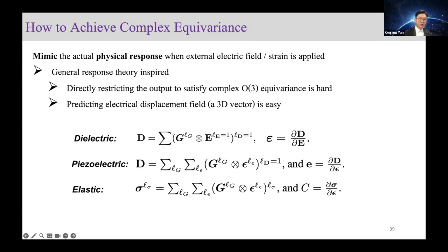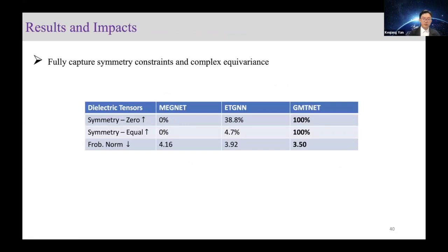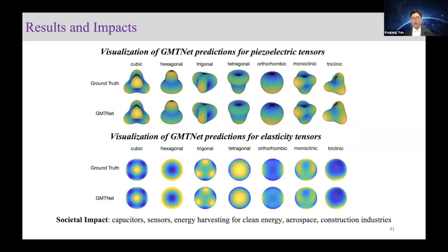I will not go into too much detail of these equations, and here we show the results. We achieved 100% success rate in satisfying all symmetry constraints, while previous works can only achieve 0 or limited to less than 10%. And we also achieved the state-of-the-art Frobenius norm, which is a metric favorable for evaluating the difference between matrices. Here, I also show some visual demonstrations to show that our predictions satisfy all the spatial properties of these piezoelectric tensors, dielectric tensors, and elastic tensors.